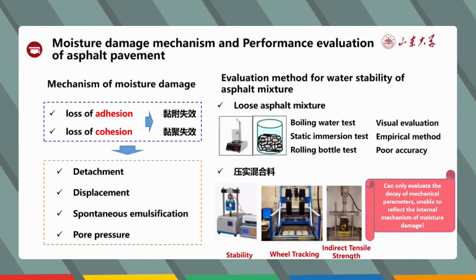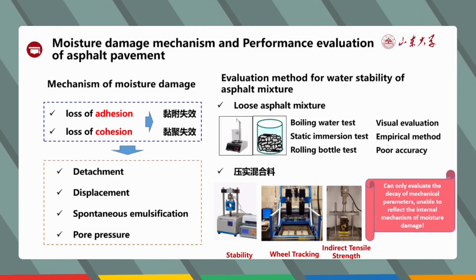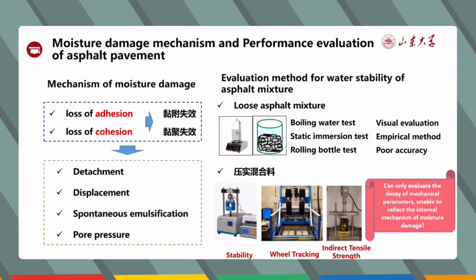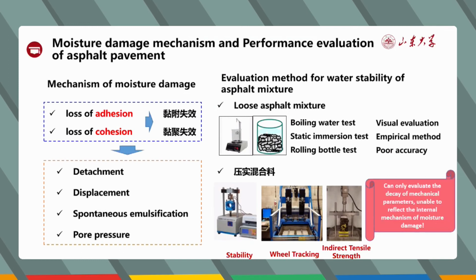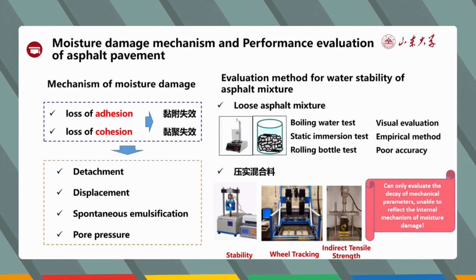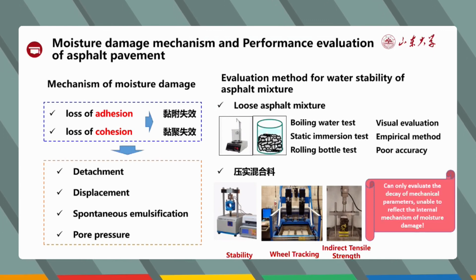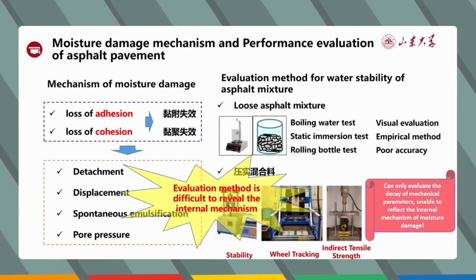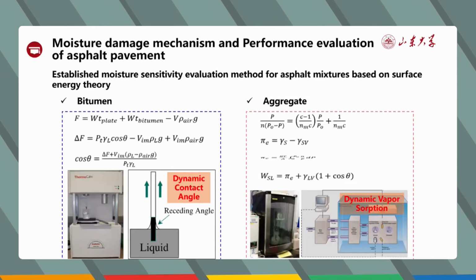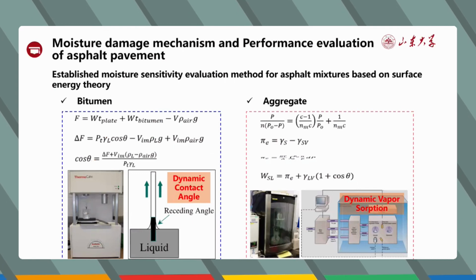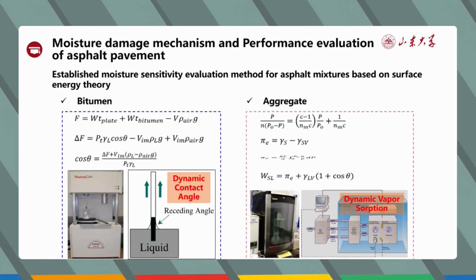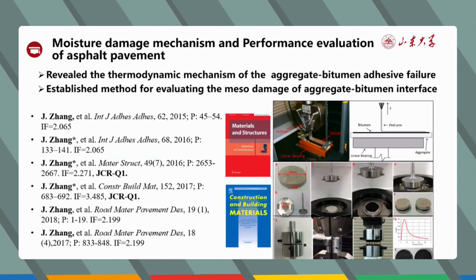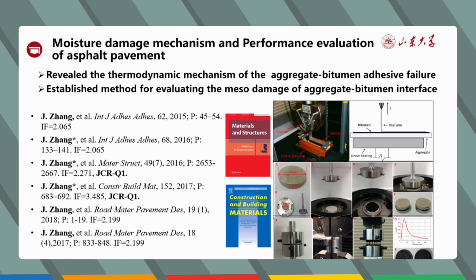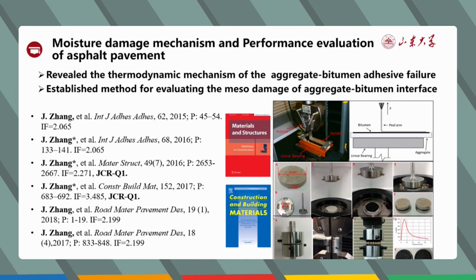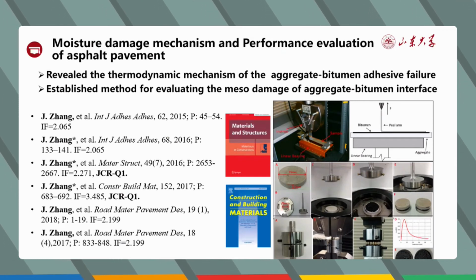In the past, there were many experimental methods used to evaluate the moisture damage and the water sensitivity of asphalt mixtures. But these methods can only evaluate the decay of mechanical parameters, and it is difficult to reflect the internal mechanism of moisture damage. Because of this, we established a moisture sensitivity evaluation method for asphalt mixtures based on surface energy theory. We also used this method to reveal the thermodynamic mechanisms of aggregate bitumen adhesion failure. We also established a method for evaluating the meso damage of the aggregate bitumen interface.